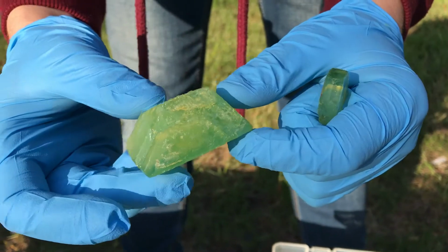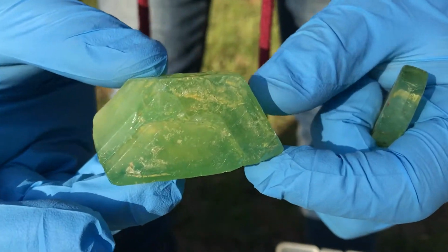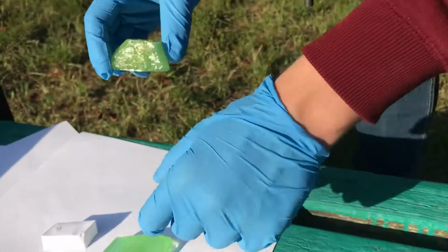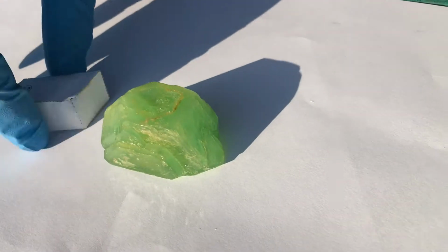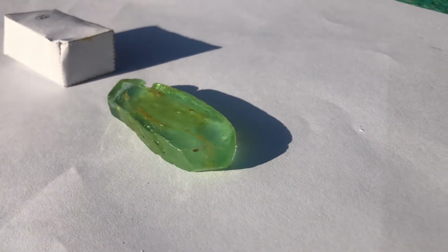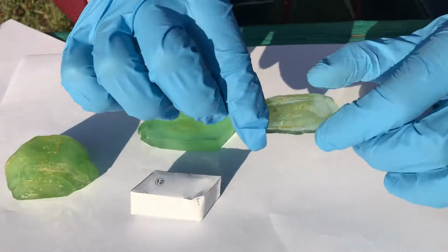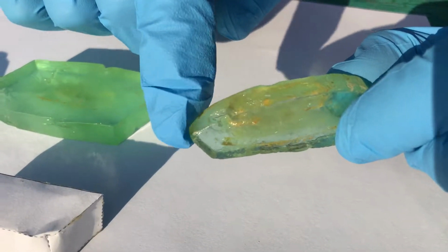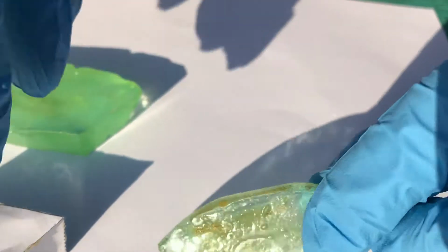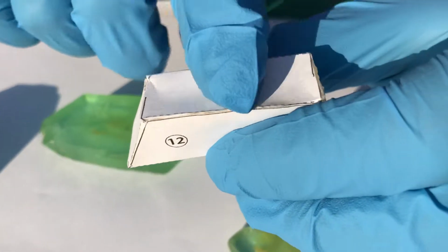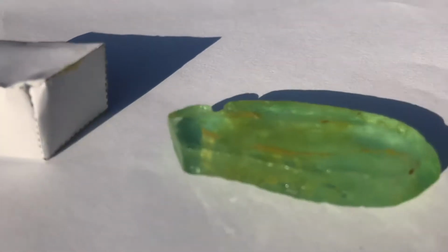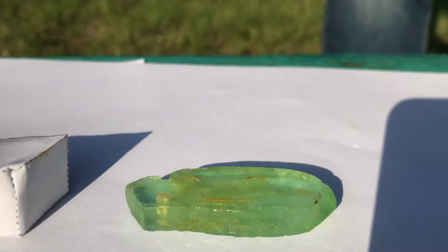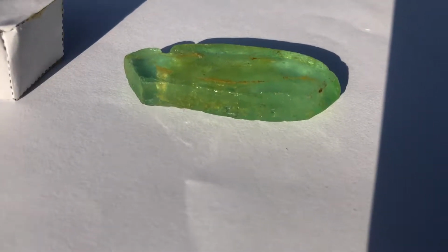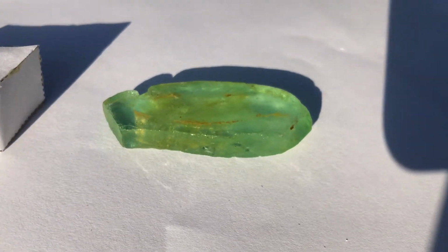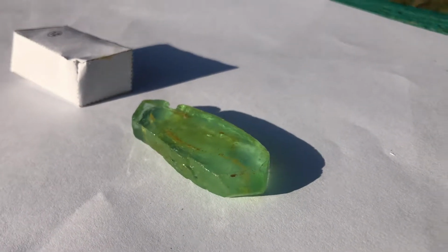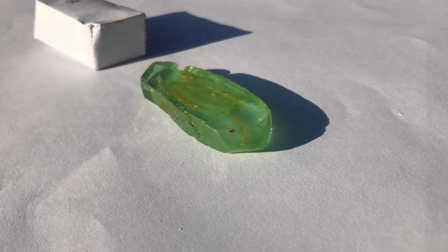I have 2 more crystals, and as it can be seen, one is more transparent and the other has a completely different form. The more transparent one was one of my experiments. As you can see, it has a rounded edge. As it was initially thought, you cannot change the shape of a crystal that is determined by its crystal lattice. However, I have achieved a modification of its shape by not letting the crystal a physical space where it can grow. It grew near a wall of the container, so that I forced the crystal to evolve in a condition of pressure.